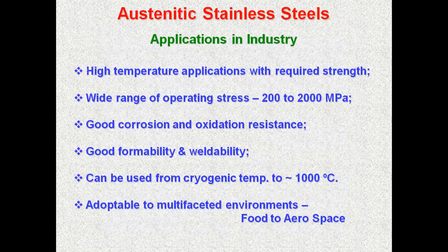What are the applications typically? To look at the high temperature applications with required strength, probably from cryogenic to 1000 degrees Celsius, a wide range of operating stress from 200 to 2000 megapascal, good corrosion and oxidation resistance from atmospheric to acidic conditions, then it is acceptable to multifaceted environments from food to aerospace. So it's a very versatile stainless steel, austenitic stainless steel. Based on the type of the stainless steel, you can use it for various applications.